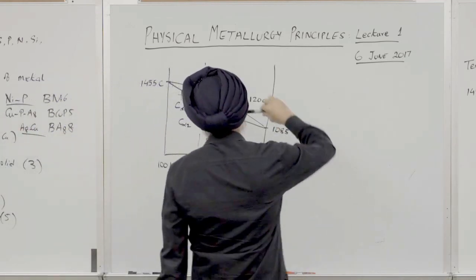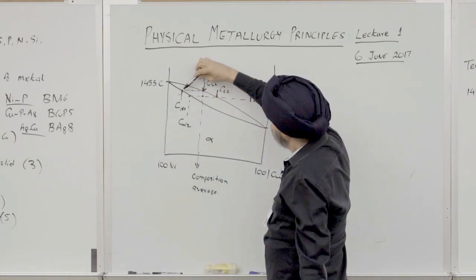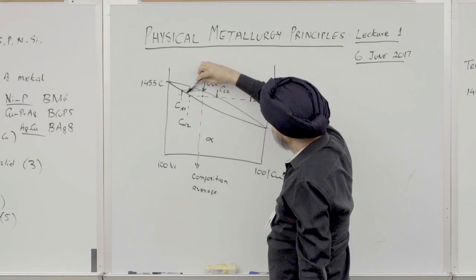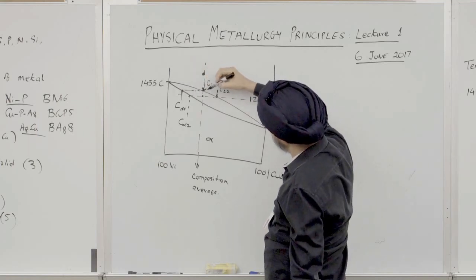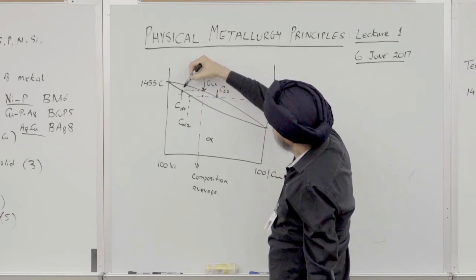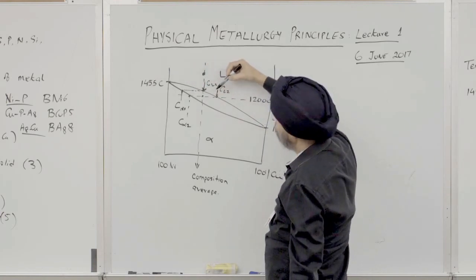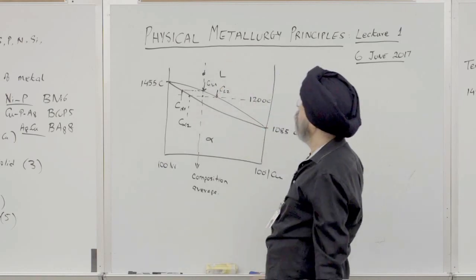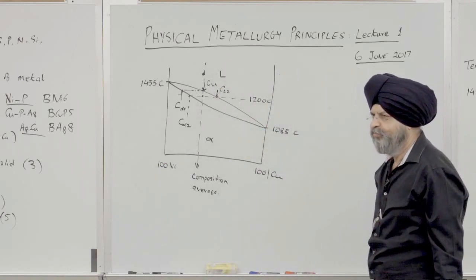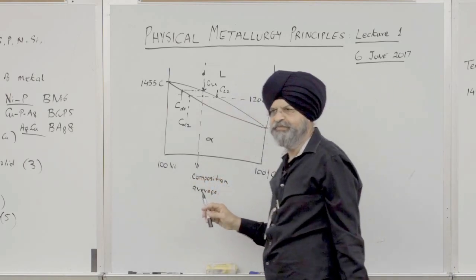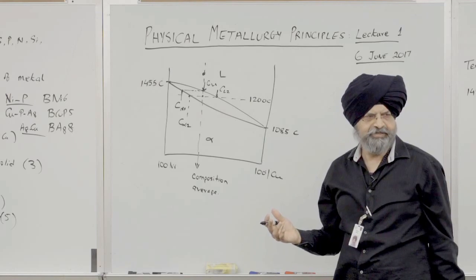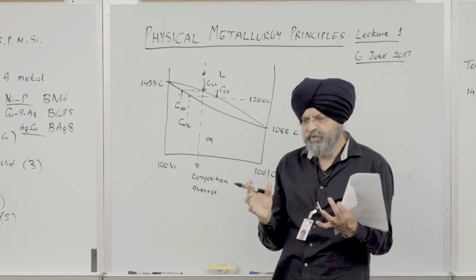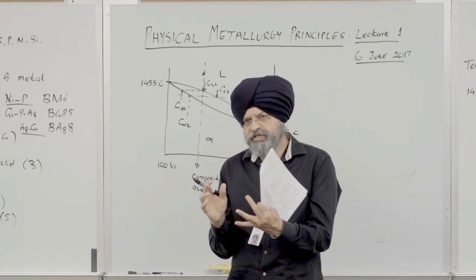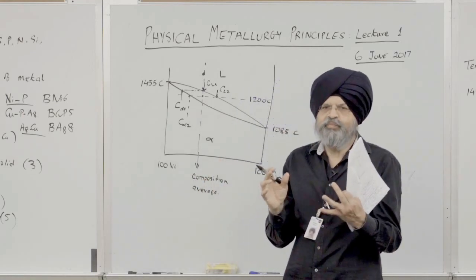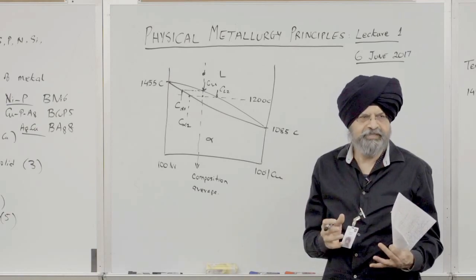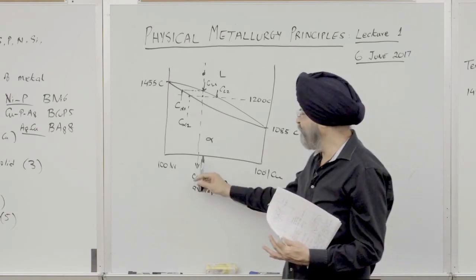So notice, as we're cooling down, the copper content of the solid is increasing. When we went from this temperature to that temperature, the copper concentration went from here to there, right? But the liquid composition also increased. But the average composition doesn't change. That's not intuitive, right? So in my melt, I have some solid and some liquid. We're cooling both down, and both of them are gaining in copper. So go figure. But the average composition doesn't change.